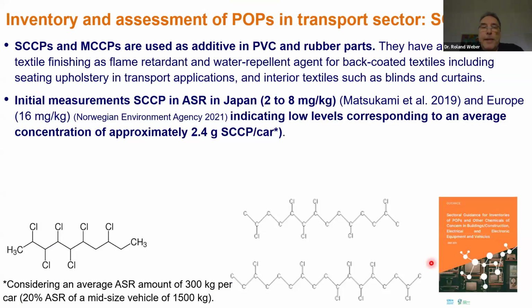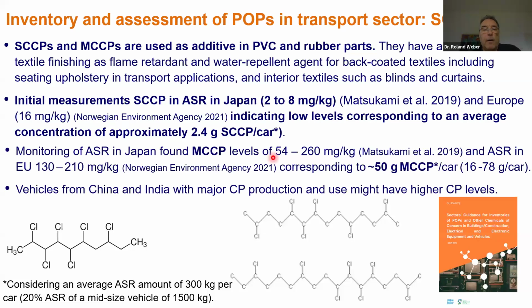Looking to SCCPs and MCCPs, which are additives in PVC. Also here we have a few data from the Norwegian study and from Japan. So here in Japan, the initial measurements of automotive shredder residue was SCCP between 2 and 8 milligram per kilogram. And the levels in Europe was 16 milligram per kilogram. So you see also very close by a factor of 2 or 3, indicating overall low levels corresponding to an average of around 2.4 gram SCCP per car.